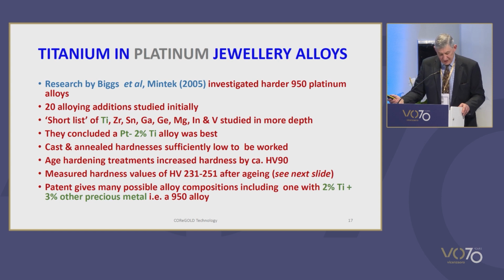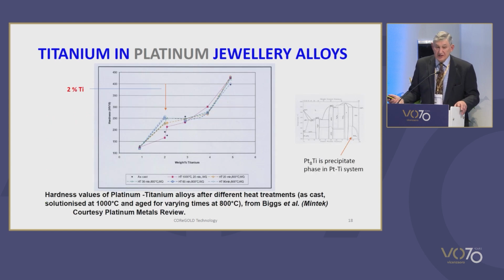depth. This work, along with consideration of other aspects, allowed the conclusion that the best alloy was a platinum 2% titanium alloy. This had cast and annealed hardnesses sufficiently low to be easily worked and formed, but with subsequent heat treatment, the hardness value could be increased by about 90 Vickers. Hardness values after aging at 800 degrees of 231 to 251 Vickers were measured, as we can see in the